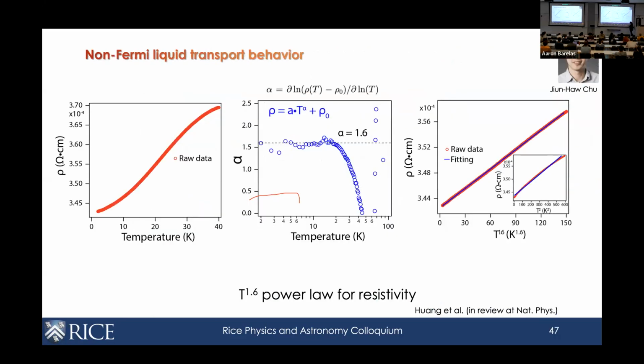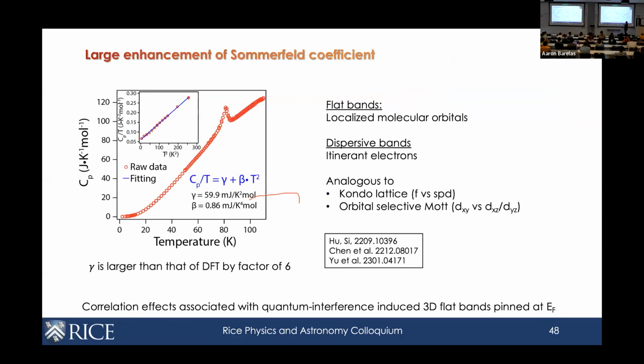Here, to make connections to macroscopic material properties, we also collaborated with Chu's group at Washington. They did the measurement of the resistivity, and they can see that as a function of temperature there's a power law dependence, and this deviates from the T-squared behavior expected for Fermi-liquid behavior. So this suggests non-Fermi-liquid behavior, as well as a large Sommerfeld coefficient, which suggests that the mass is enhanced by a factor of 6 in this material. That is very consistent with our observation of a flat band at the Fermi level, right?